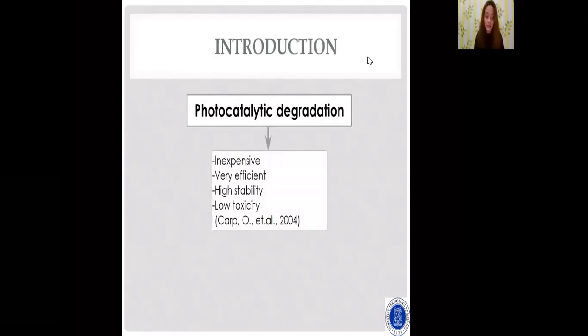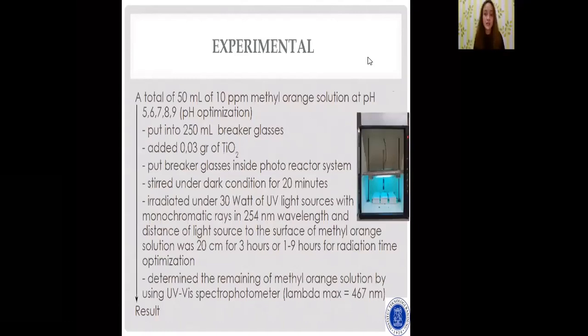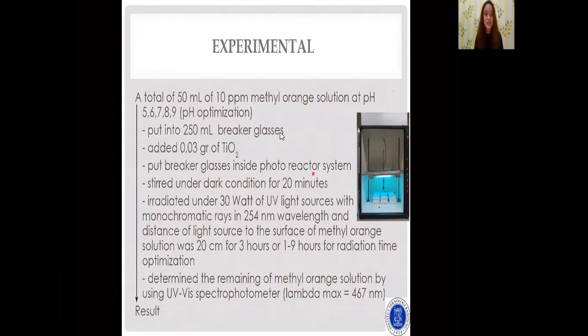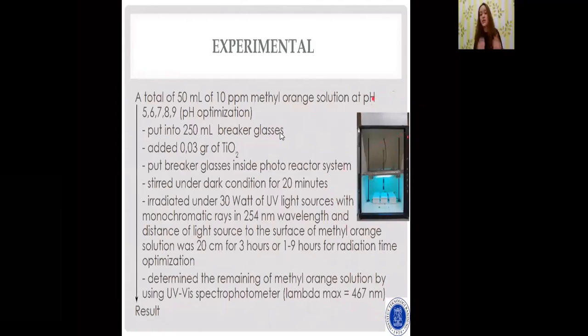Titanium dioxide compound can be synthesized by sonochemistry, hydrothermal processes, hydrolysis under acidic condition, or sol-gel methods. But here we chose the hydrothermal method. So here is the experimental method in our research. A total of 50 milliliters of 10 ppm methyl orange solution at pH 5, 6, 7, 8, and 9 was put into a beaker glass, titanium dioxide was added, and the beaker glasses were put inside the photoreactor system, stirred under dark condition for 20 minutes, irradiated under a 30 watt UV light source, and the remaining methyl orange solution was determined using a UV spectrophotometer with the lambda maximum at 467 nanometers. Here you may see the photoreactor that we use in our laboratory.